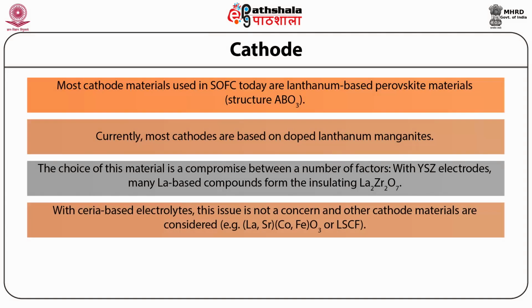With ceria-based electrolyte, this issue is not a concern and other cathode materials are considered. For low temperature cells, the conductivity of LSM, that is lanthanum manganite, is inadequate and other materials such as strontium doped lanthanum ferrite, that is LSF, are considered. Thermal expansion coefficients of cathode materials that closely match with YSZ are considered.